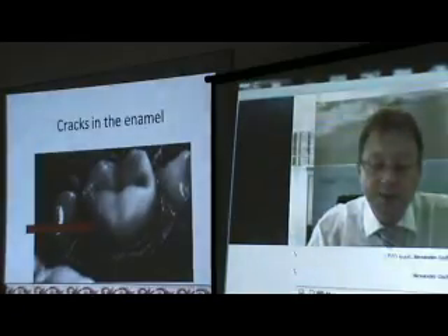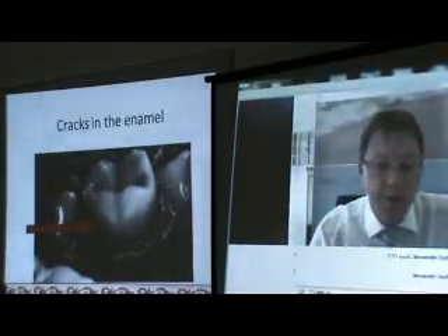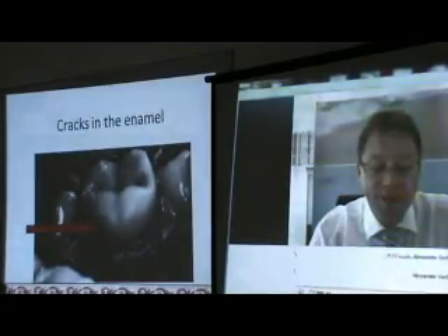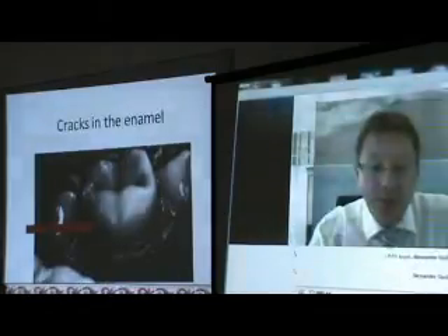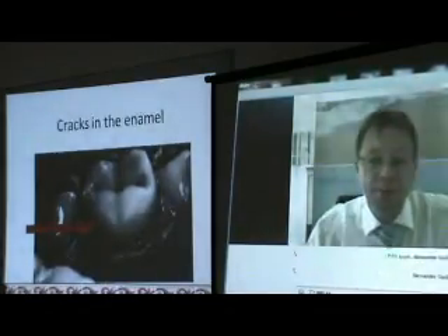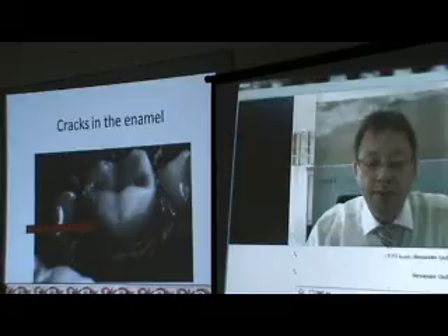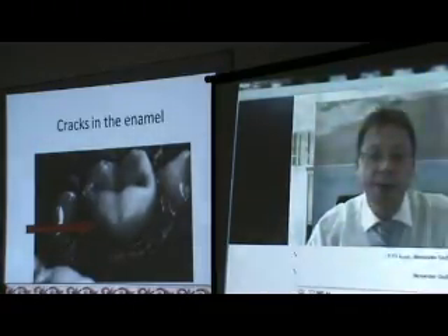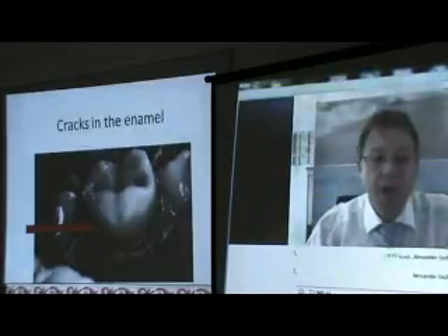So during these 30 minutes, the composite has actually pulled on this natural enamel and has deformed it. And because the natural enamel is extremely rigid, it was enough to create all of these fissures on the natural enamel.